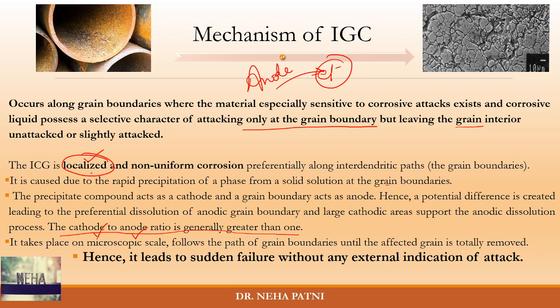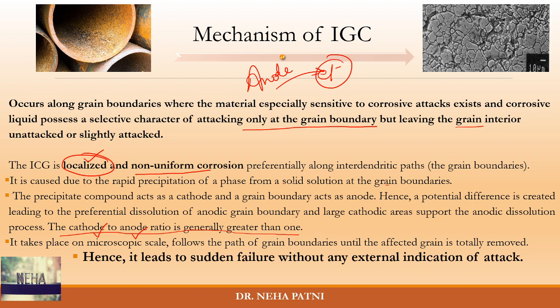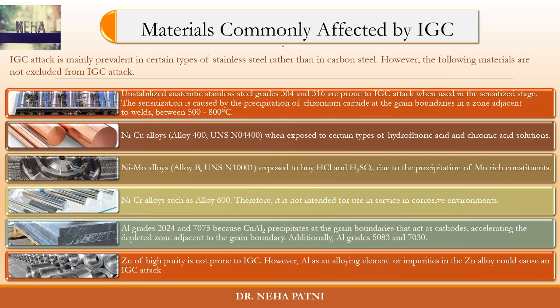IGC is non-uniform corrosion because the precipitate does not form uniformly — wherever it precipitates, only that area becomes depleted and anodic. It preferentially takes place at the grain boundary. In conclusion: the anodic portion is the boundary, the cathodic portion is the center. It leads to sudden failure, which makes it extremely dangerous — you cannot see it because it takes place on a microscopic scale, and it only surfaces after the entire grain is affected.